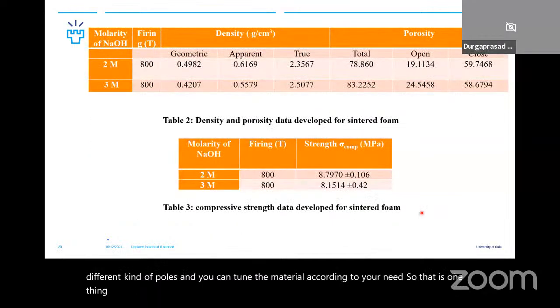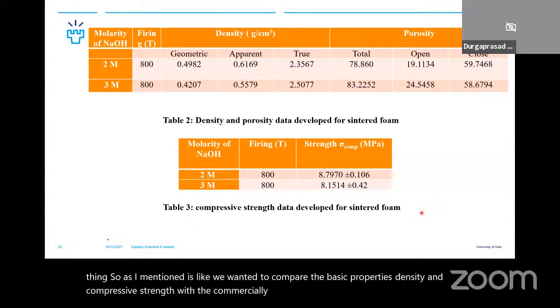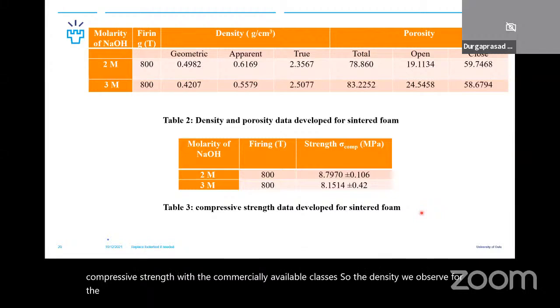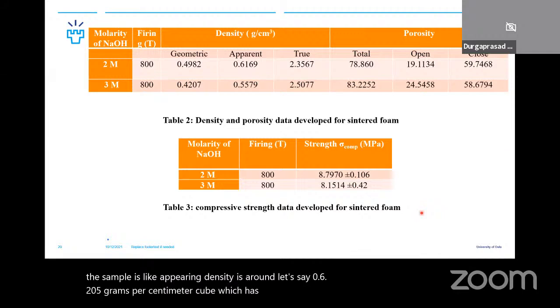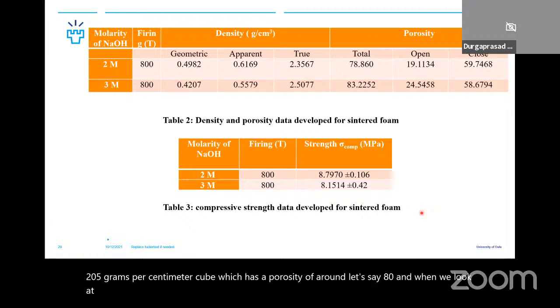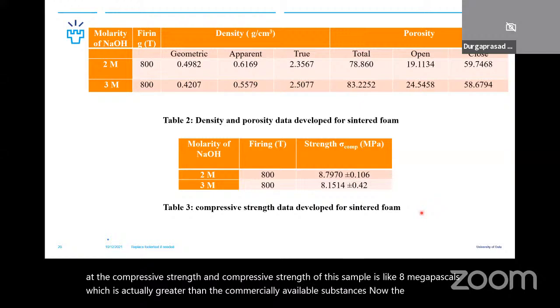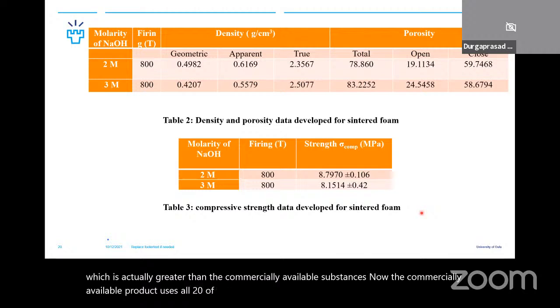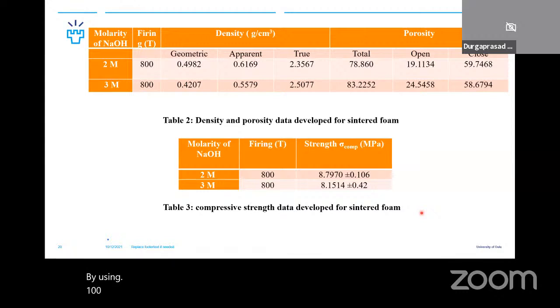As I mentioned, we wanted to compare basic properties like density and compressive strength with the commercially available glasses. The apparent density we observe for the sample is around 0.5 to 0.6 gram per centimeter cube, which has a porosity of around 80%. The compressive strength of this sample is 8 megapascal, which is actually greater than the commercially available substances. The commercially available product uses only 20% waste and 80% natural resources, and we created this using 100% waste product. So this is kind of an achievement.